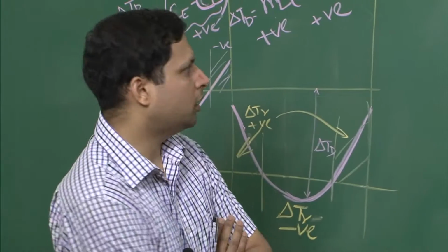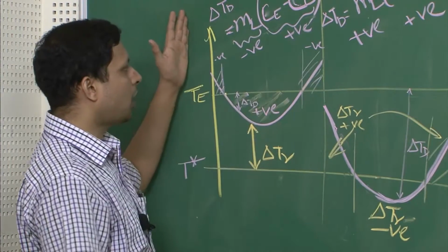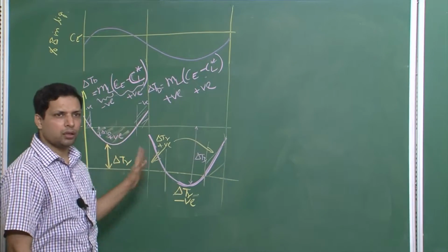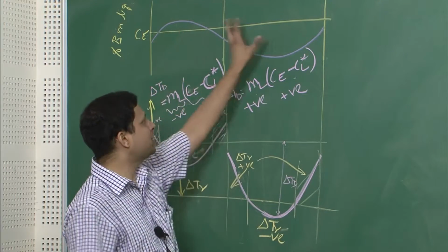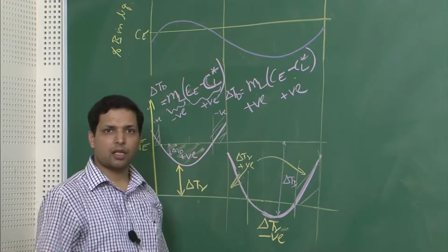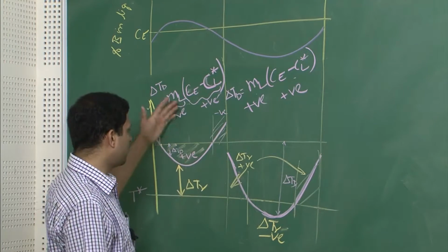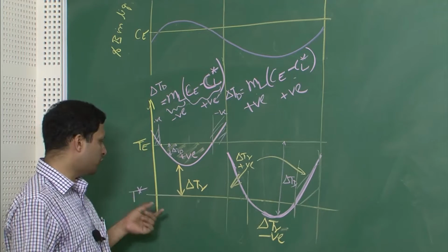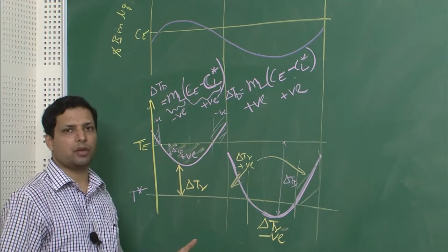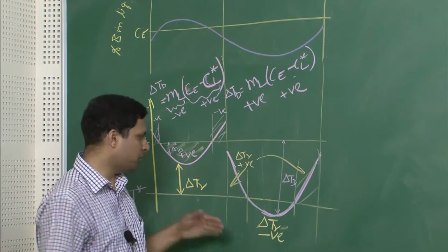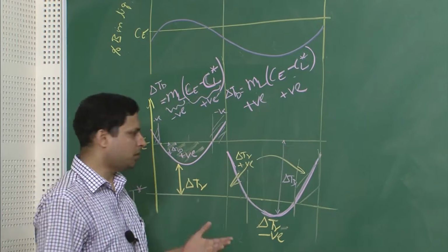We were discussing planar front solidification in polyphase alloys, and we have looked at how the concentration distribution would be in a polyphase alloy when we have, let us say, two phases alpha and beta. This was the alpha phase, this was the beta phase, and this is a schematic of how the composition difference is there in the alpha phase and the beta phase, and what the corresponding temperature difference is. Overall T star, the total undercooling, remains constant, because you remember we have an additional phase, so fewer degrees of freedom, and we are not externally adjusting T star. It is adjusted by the system on its own.